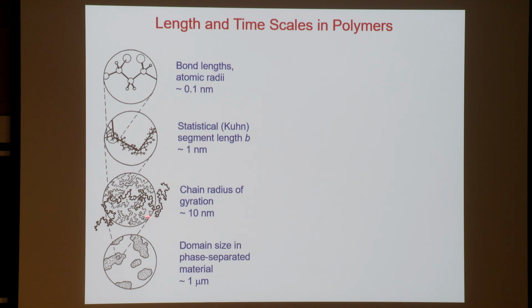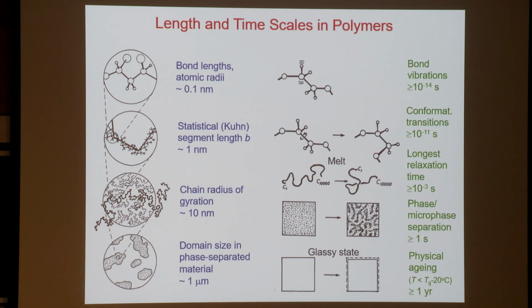We have structure at the level of the entire chain, typically quantified through the radius of gyration. And for usual molecular weights, this can be 10 nanometers or longer. And we may even have phase or microphase separation phenomena leading to domains with characteristic sizes of 1 micrometer or larger. Even broader is the spectrum of characteristic times that one has in polymeric materials. Bond vibrations have periods on the order of tens of femtoseconds. Conformational transitions, gauche-trans isomerization, for example, in a polyethylene melt, have waiting times on the order of tens of picoseconds.